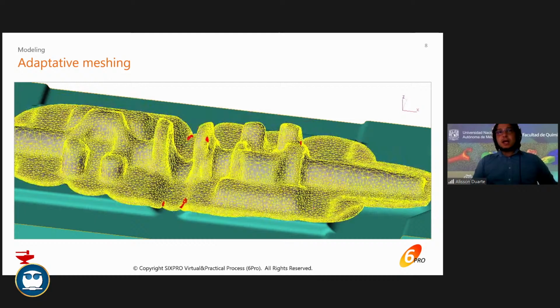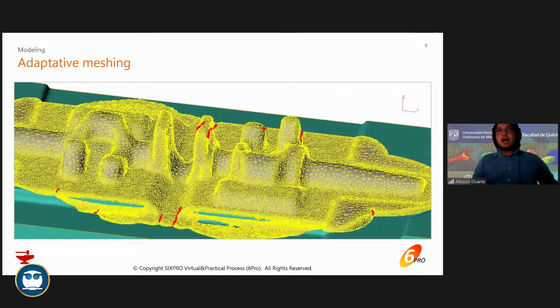It's interesting that in this case, as you see here, the part forged is this here. This is all the part forged, okay? And we have this shaft on it. And as you can see, in these areas, we have bigger elements, and this area here is a very thin area, with smaller elements over here, right?